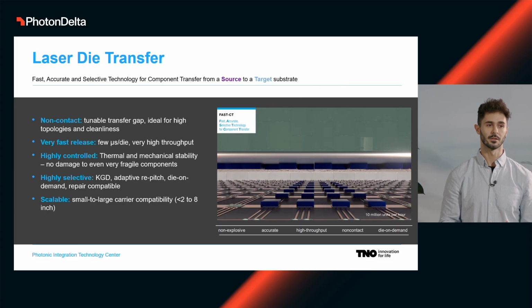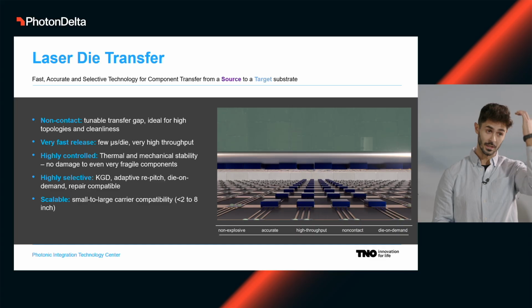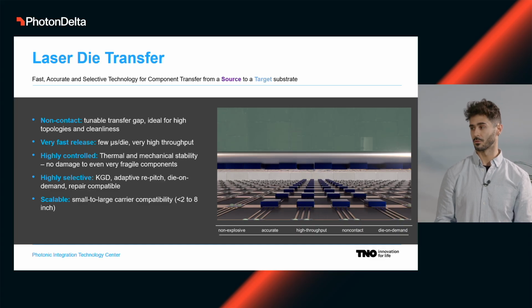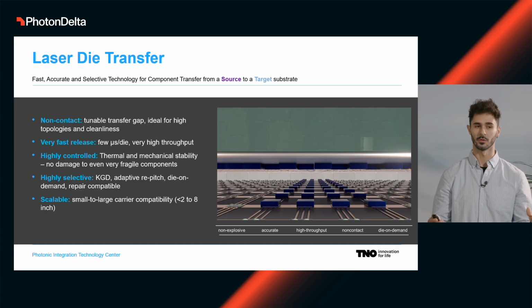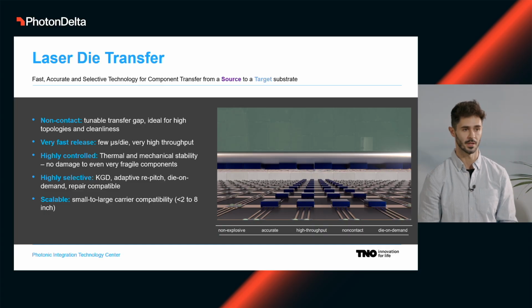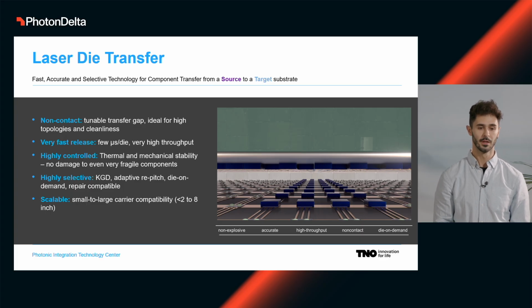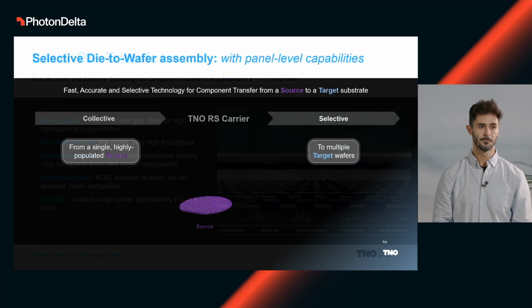It's a non-contact transfer technology. It's ideal if you have topologies, and also for cleanness, and I will talk later about why. The release of each component is very fast, a few microseconds per die, so it can lead to very high throughputs, and it's highly controlled. You don't damage the component when you transfer it. It is also extremely selective, so you can have the known-good-die approach. You can transfer one component without affecting the neighboring one, and repitch densely populated components into whatever other kind of design you want, and it's compatible with different substrate sizes.